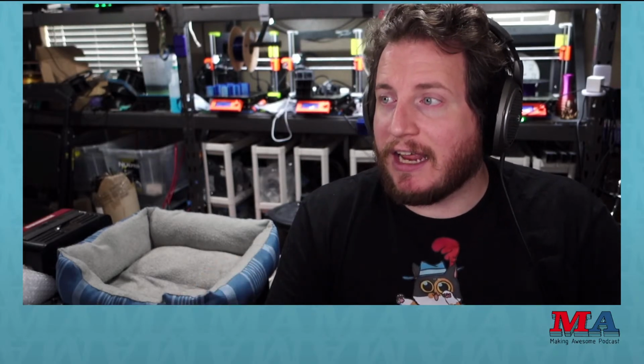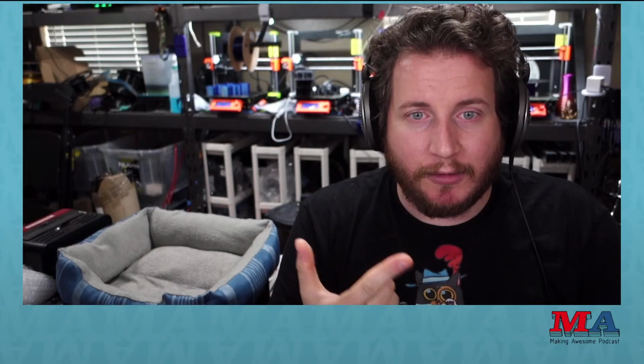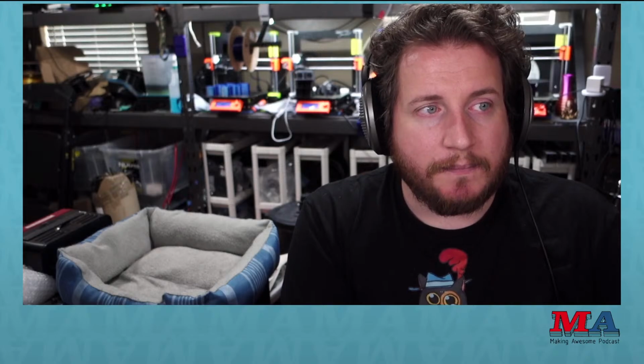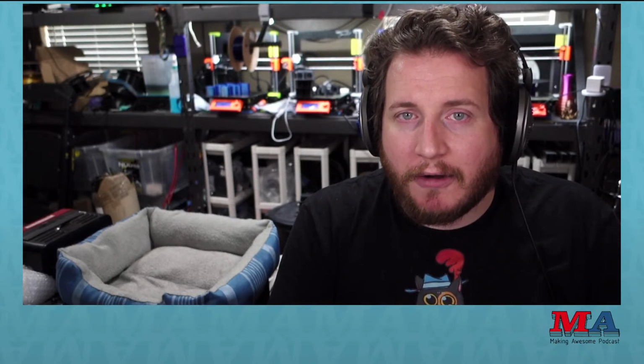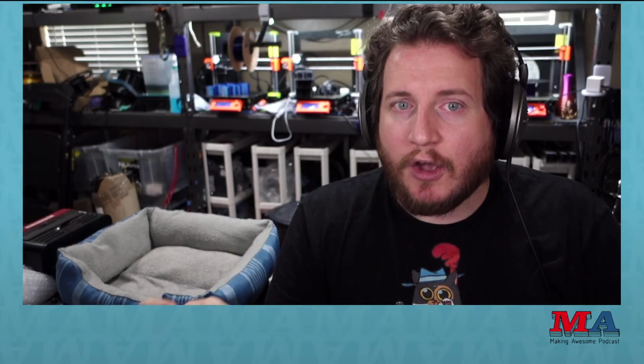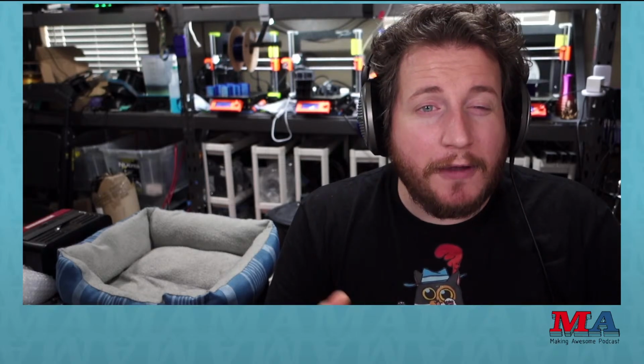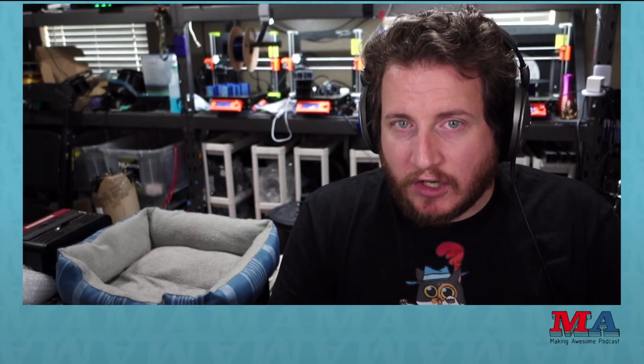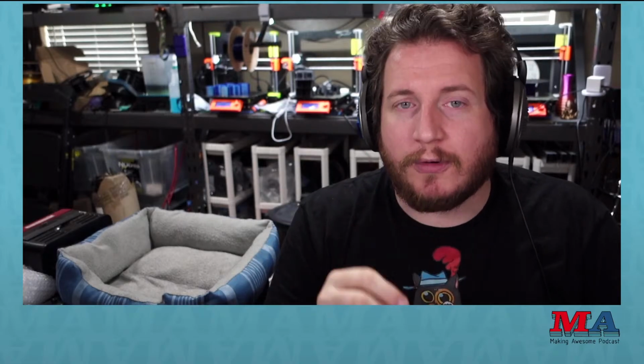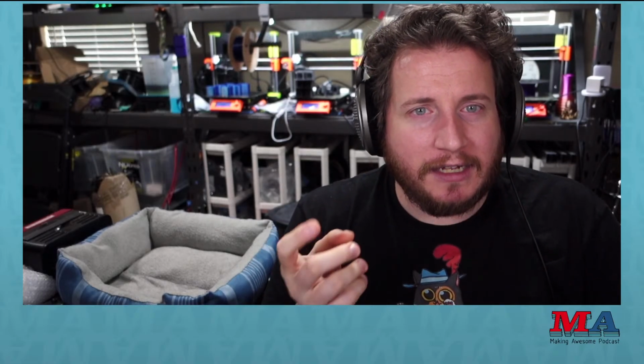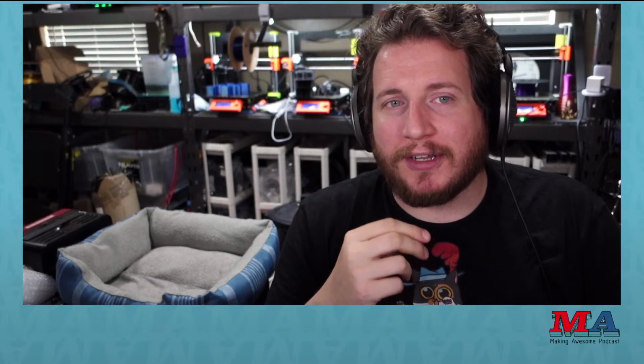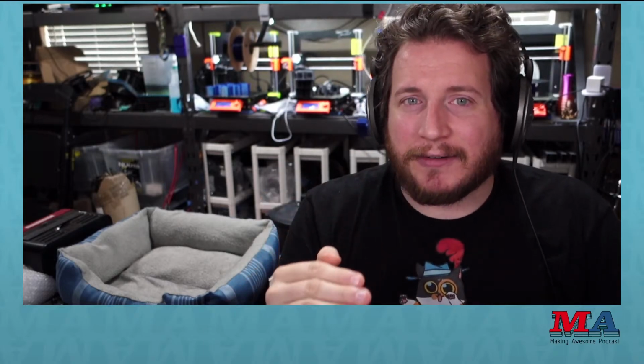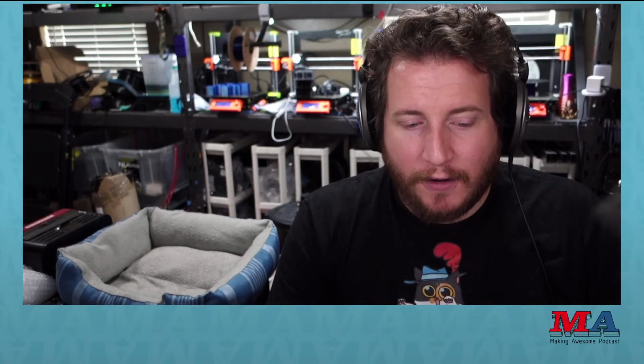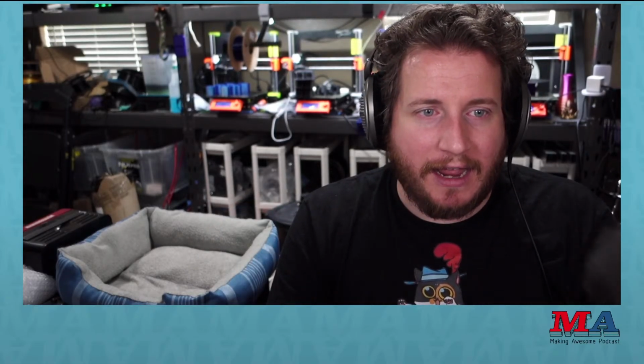As someone that lives in an area that is incredibly high heat, incredibly high moisture, but we do have central air, at least I'm not too sweaty indoors. But if you do get too high of an ambient air temperature, your PLA will start to fail. At around 40 degrees Celsius, PLA will start to heat creep and not move through a hot end very effectively. Hilariously, it does a lot better through a non-all-metal hot end at higher temperatures because that PTFE can actually insulate the filament itself from those nasty ambient air temperatures.